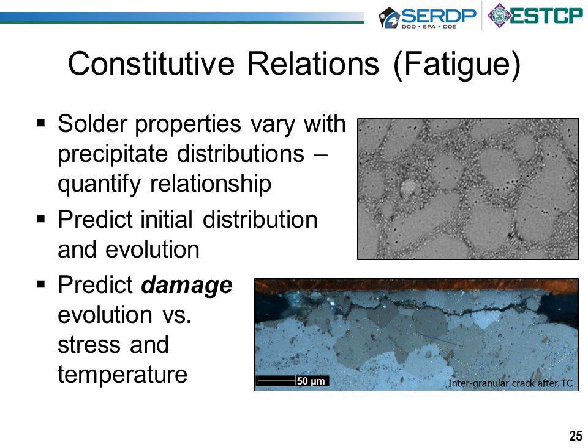So it has, as you can see here on the top of these two images, these colonies of precipitates in the tin. And these precipitates really determine or dominate the deformation properties. And so what we need to do is predict how they're distributed and how these distributions change. And then we're going to predict how the damage evolves with the stress and temperature, and again with the distributions of these precipitates.